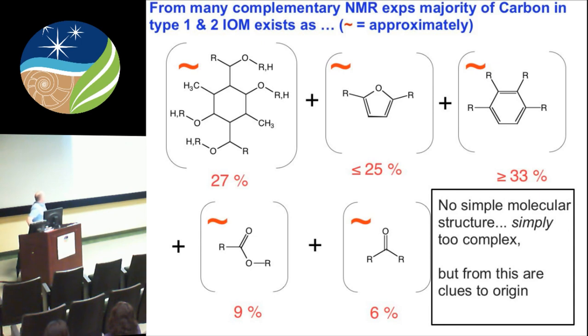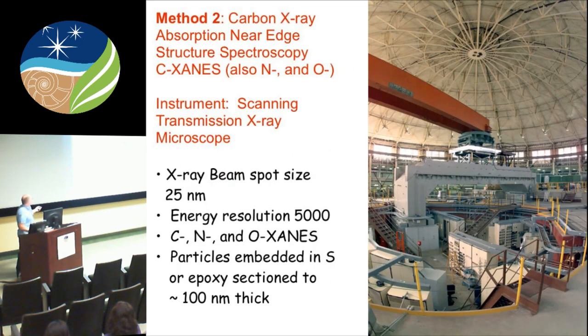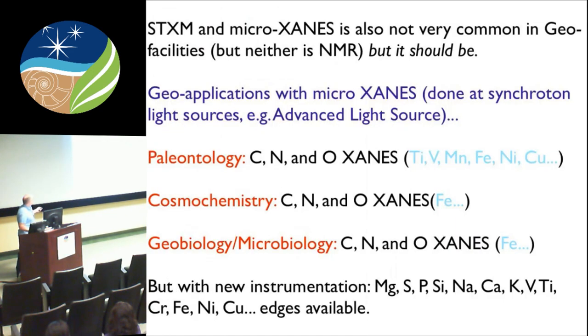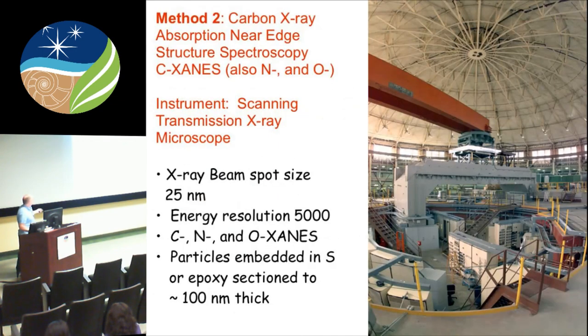Now, I'll get into the second method, which is carbon X-ray absorption near-edge structure spectroscopy, or carbon XANES. It's a very powerful tool that works down to a 25 nanometer spot size on a really good day, probably 40 nanometers typically. It has high energy resolution, and you can work on carbon, nitrogen, oxygen K-edge.